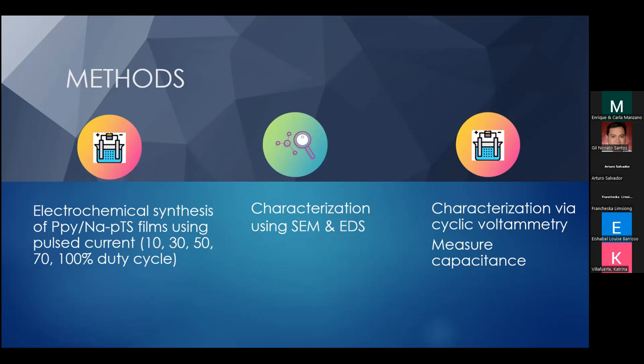So what did we vary in this study? We varied the current that we applied. The current density was constant, but we varied the duty cycle. It's called a pulsed current source. So we varied the duty cycle from 10, 30, 50, 70, and 100, which is basically DC current.